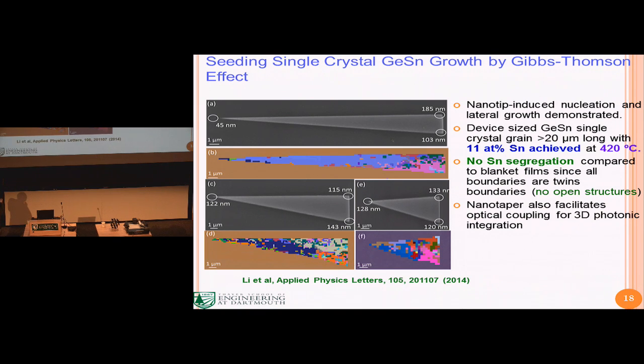So if you anneal the material, you find the crystal growth from this sharp tip really dominates the entire structure. The one with 100 nanometers is getting less, and the 200 nanometer tip has very little growth in this case. Interestingly, we find that all the green boundaries here are twin boundaries. We do not see any tin segregation on the surface anymore. In this case, we can incorporate even more tin into the germanium, which is 11%, analyzed by micro-Raman analysis.